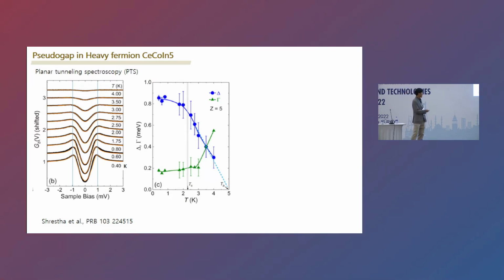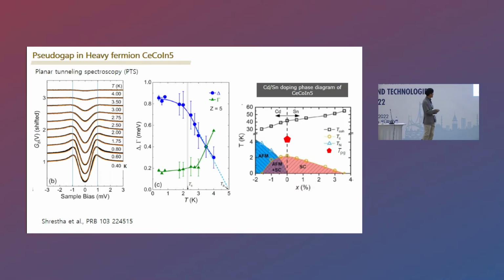However, if you study heavy-fermion compounds, then you know that there are a lot of competing phases around. For example, this is cadmium, the negative, which is hole doping, and tin doping, which is positive, the electron doping, to cerium cobalt indium-5. You can see that the coherence temperature gradually increases, but the superconductivity shows a dome shape centered around the pure compound, and the antiferromagnetism is nearby with a very slight amount of cadmium doping, indicating that it's difficult to make a definitive conclusion based on this, or to rule out the possibility of a competing order as an origin of pseudogap.